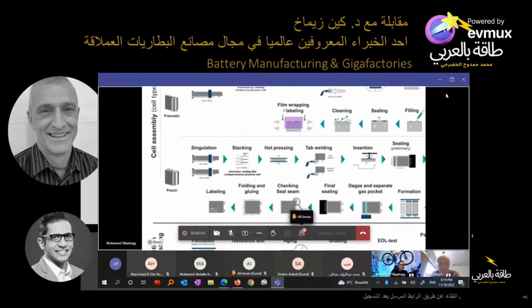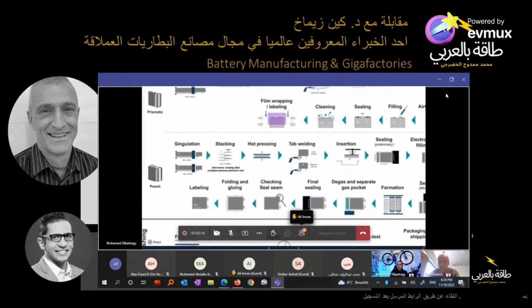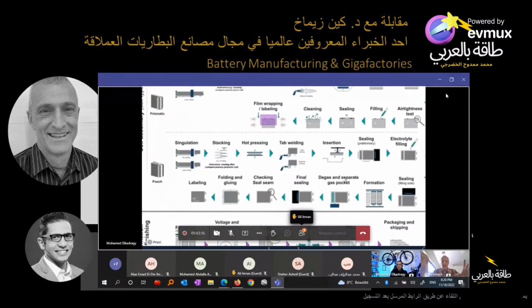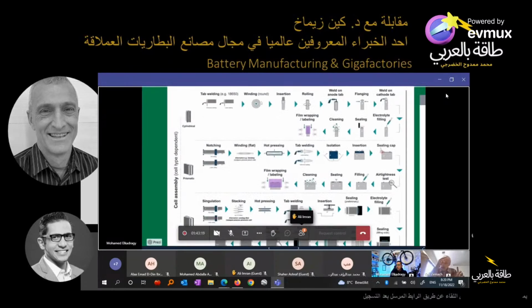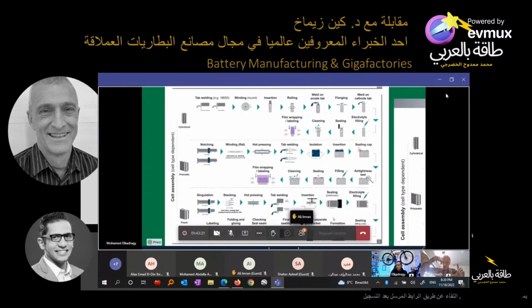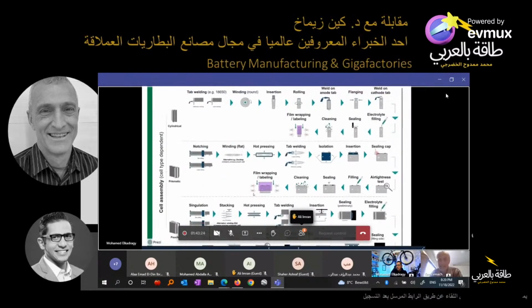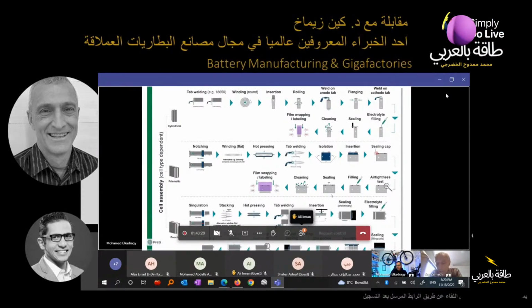You're not completely sealing it because now we've caught up with the cylindrical. Now you need to get that electrolyte in, so you've got to fill your electrolyte. Now, on a small cylindrical cell, that electrolyte you put in however many grams you're going to put in, 4 grams, 7 grams, depends on the size of your cell. In a giant prismatic cell, like some of these big cells, you've got a tiny little fill hole. And so you put in all the electrolyte you can, and you can't get in enough because it hasn't soaked in, because there's a transport problem.